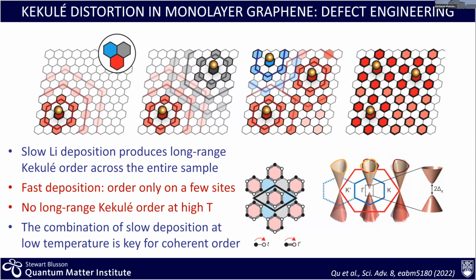So by using temperature, a few Kelvin, as a way to modulate the kinetics of the system and slowing down the deposition, the suggestion is that it is a long range order, and the only way we're able to build it is if these are indeed in phase on the same registry. The opposite is very intense deposition, or going too high in temperature, and eventually everything goes away. There's a question back there, I think.